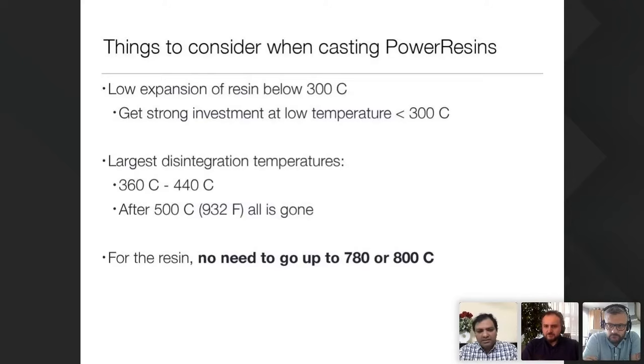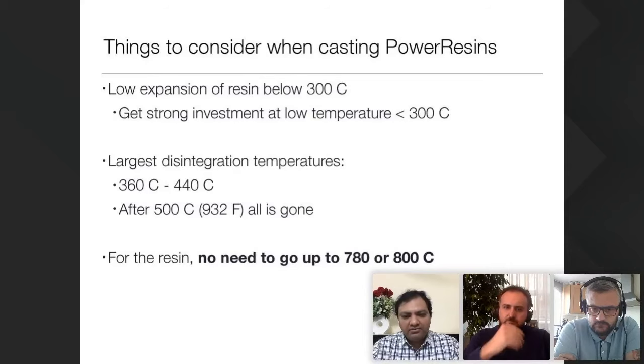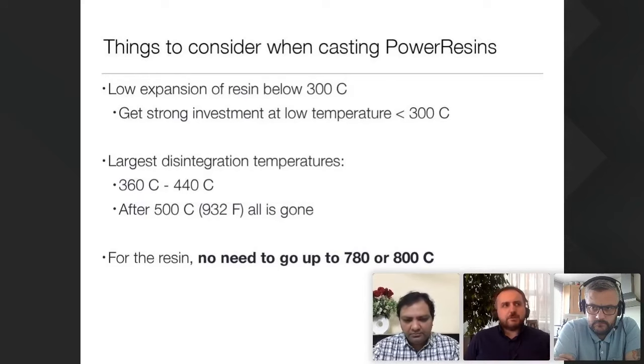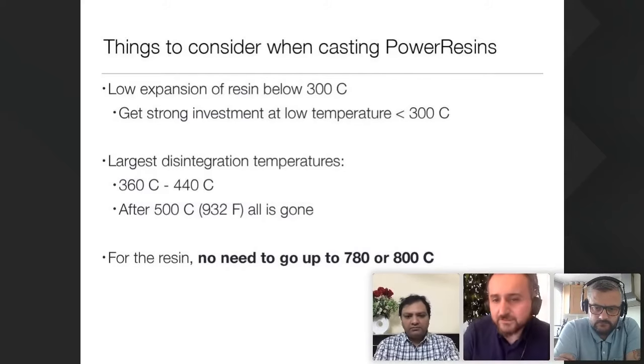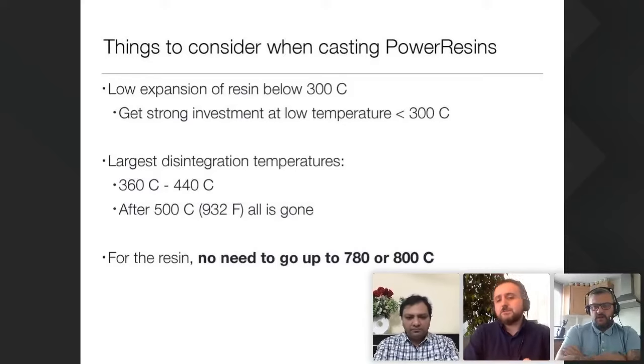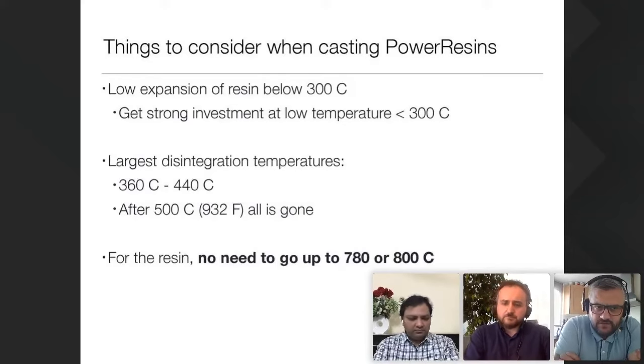You're on the same ground, I guess. Yes, I think there is no shortcut on that. People try to make it shorter - immediate invest and then put it into the burn-off furnace. It's a very big mistake that they do. I think there are a couple of papers where 2 hours is a good time, but 3 is slightly even better, but 90 minutes is definitely the minimum. If you don't leave it 1.5 hours, you can have really serious issues with the strength.